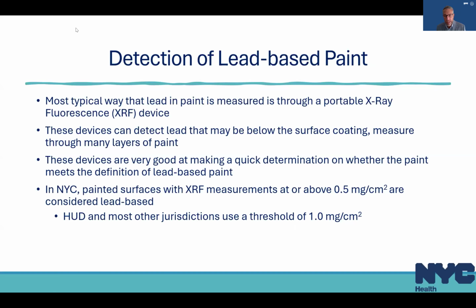So like most other health departments, the way we measure lead in paint is through a portable X-ray fluorescence device. We'll call it XRF from here on out. It is a very convenient device that is able to detect lead through multiple layers of the surface coating, so that you're not only testing the surface layer, but you're testing the embedded lead. And it's very good at making a quick determination on whether that surface you're testing meets the definition of lead-based paint.